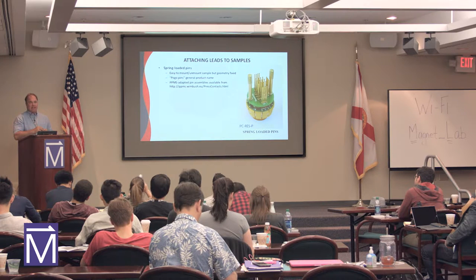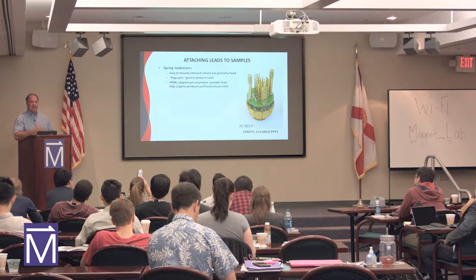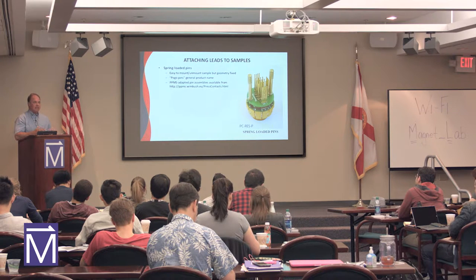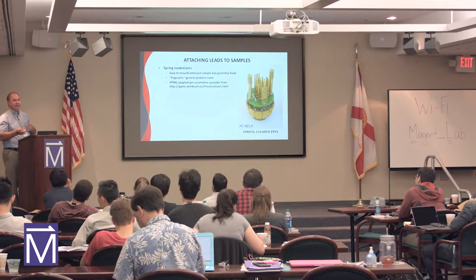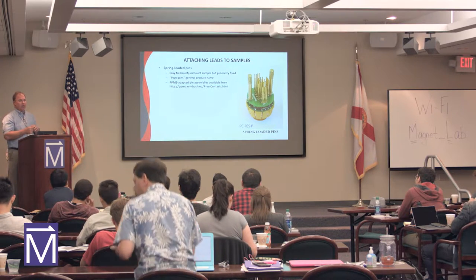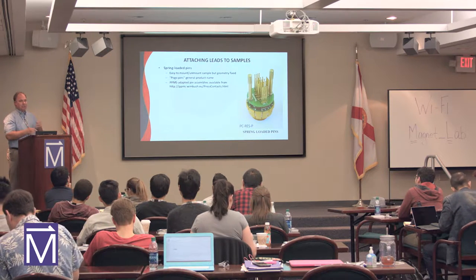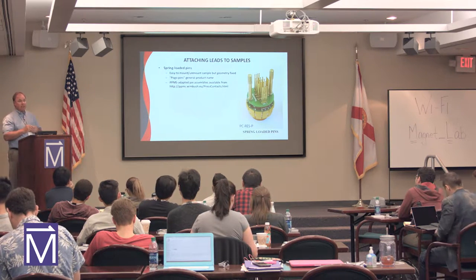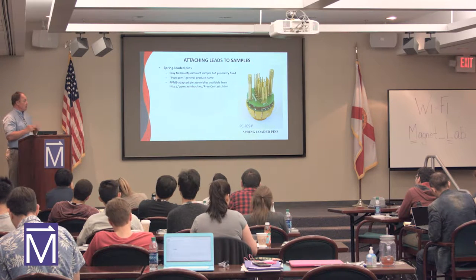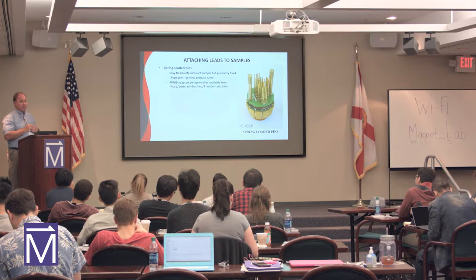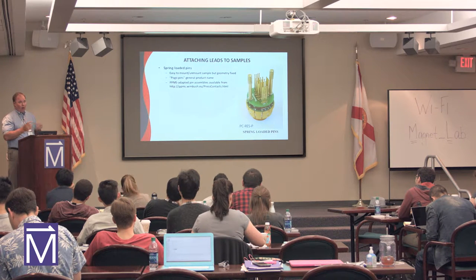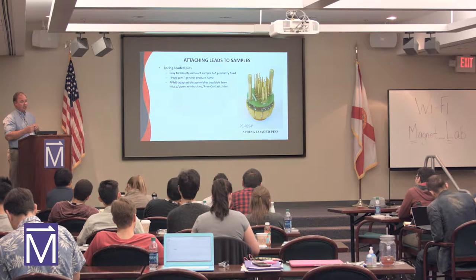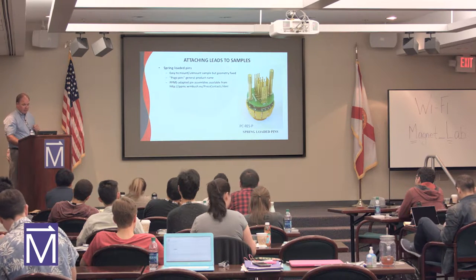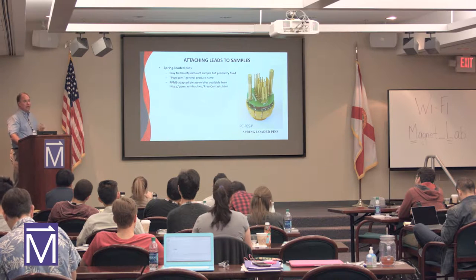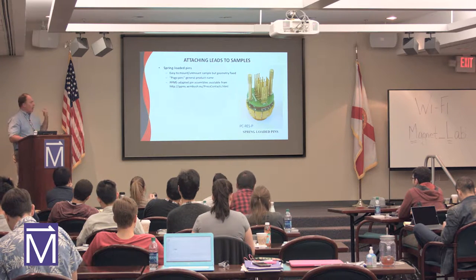You may not have good contact, right? So it may not be a perfect contact. These things are mechanical in nature, so they tend to degrade. But if you have a set of common samples where this works, it may be easier for you than doing a wire bonding or soldering contacts on your sample. So if it's something routine and you can get away with this type of pogo pin, maybe you can make more sample measurements. But there's a number of different pinout configurations, so you can do things like the Hall four-wire measurement or a Van der Pauw type measurement on your sample. So there's a few ways you can do it, right? Silver paste, two types of pinouts.